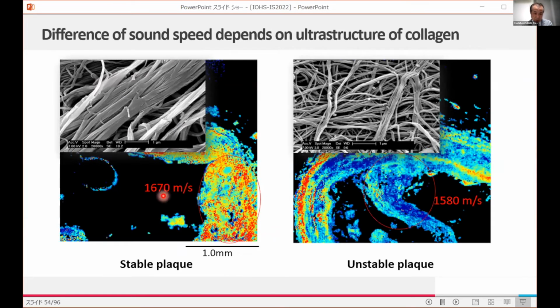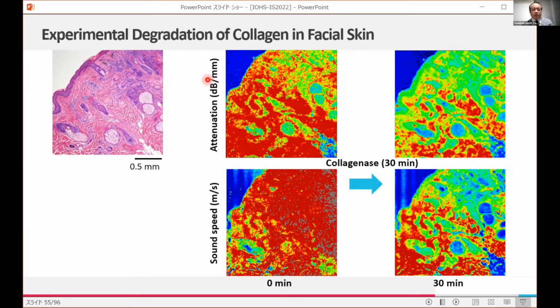Here, the sound speed is 1670 meters per second, and the electron microscope shows these very thick fibrils. And here, the sound speed is lower, and the electron microscope reveals very thin fibrils. So we can estimate this ultrastructure by measuring the speed of sound of ultrasound. And this is another experiment, degradation of collagen in facial skin. This is attenuation, this is the sound speed, and we rinsed the tissue in collagenase, and some of the collagen was degraded. Then 30 minutes later, the acoustic properties had changed.